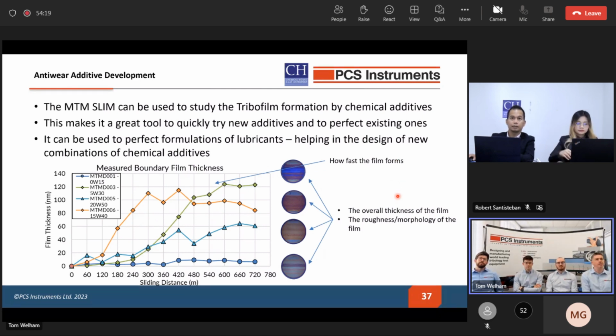So this is a typical use case showing how tribofilms evolve in different oils. We took a series of timed steps represented here by sliding distance. So we set a speed and set a duration, and from that we could work out the distance that we wanted. This compares 4 different oils, and on the y-axis here we have film thickness in nanometers. It shows how varied tribofilm formation can be between different chemistries.